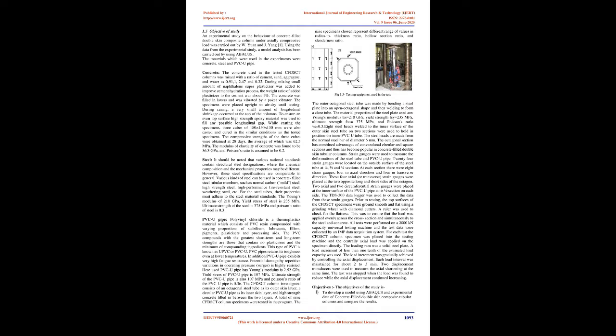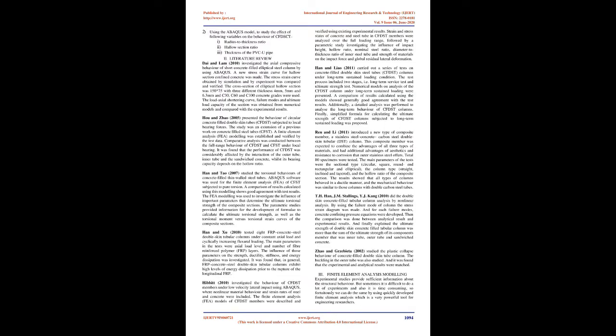Concrete. The concrete used in the tested CFDSCT columns was mixed with a ratio of cement, sand, aggregate, and water as 0.91, 1, 2.47 and 0.32. During mixing, a small amount of naphthalene superplasticizer was added to improve the cement hydration process. The weight ratio of added plasticizer to the cement was about 1%. The concrete was filled in layers and was vibrated by a poker vibrator. The specimens were placed upright to air dry until testing. During curing, a very small amount of longitudinal shrinkage occurred at the top of the columns. To ensure an even top surface, high-strength epoxy material was used to fill any possible longitudinal gap.